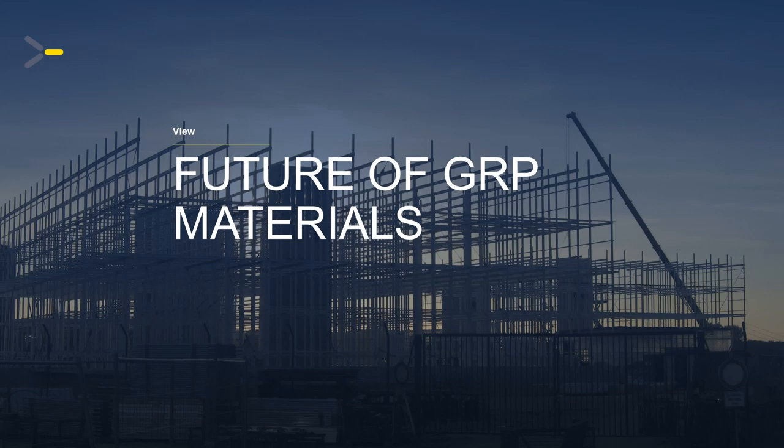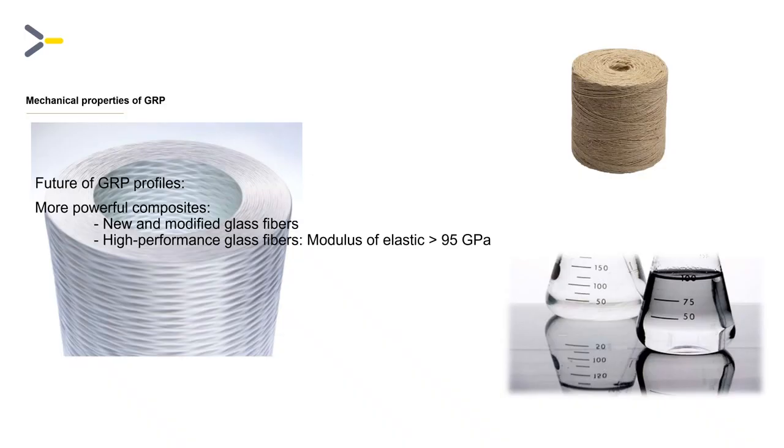The future of pultruded or fiberglass profiles can be split into two different parts. You can say the future just around the corner is to increase the stiffness of the profiles, and this can easily be done by switching to higher modulus glass. I mentioned a modulus of glass of about 75 gigapascal in one of my first slides, but today you can purchase off-the-shelf bobbins with fiberglass with an e-modulus of over 95 gigapascal. This change can be easily made since sizing types are similar.